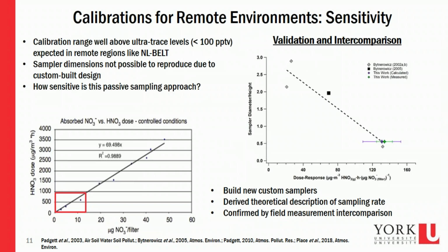This works really well in polluted environments. There have been literature reports of that before. But the challenge here was to be able to sample these at ultra trace levels, so under 100 parts per trillion by volume. The calibrations that had been done before for the sampling rates as a function of the amount of, or the exposure that you have as a function of the nitrate you collect on a filter had only been done under polluted conditions or simulated polluted conditions.